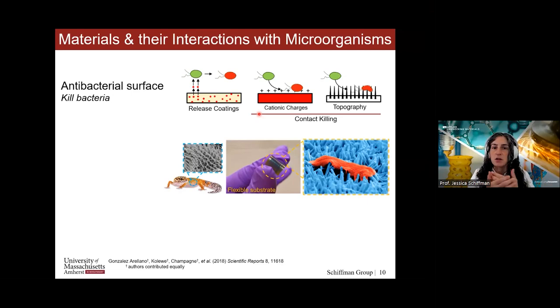Okay. Another way we can make an antibacterial surface by contact killing is to use topography. So here's a cartoon, and actually here's a table of contents graphic from one of our manuscripts that shows this very well also, of where certain topography has been shown that once the bacteria comes into contact with that bed of nails, the bacteria actually becomes inactivated. The bacteria tries to crawl away and instead it self-impales itself. When we talk about bacteria resistance, I can only imagine that bacteria would literally have to grow a much thicker skin in order to survive this kind of topography.